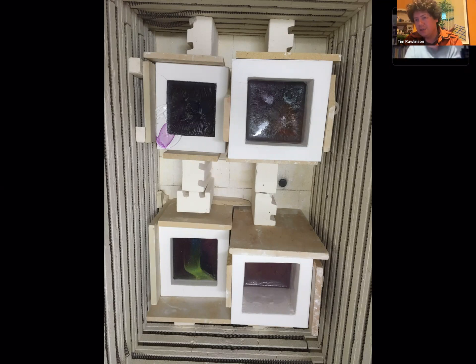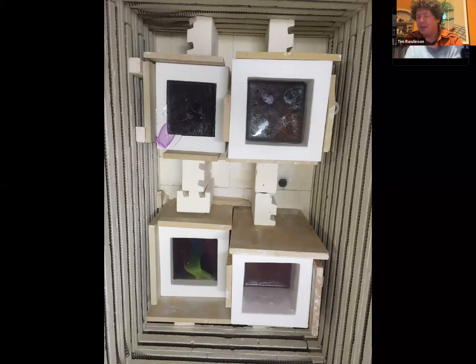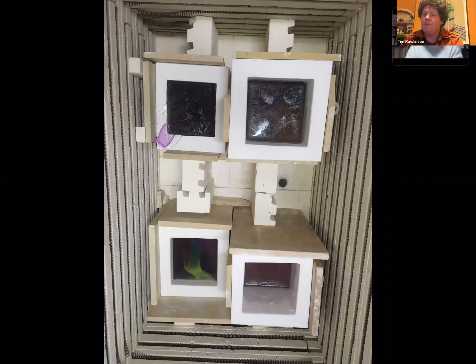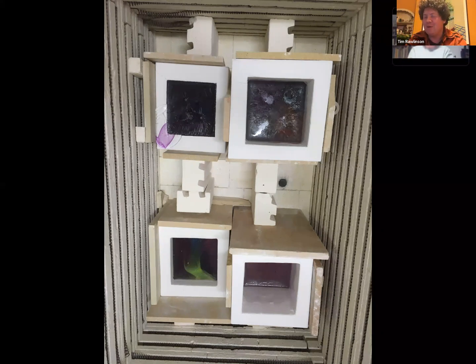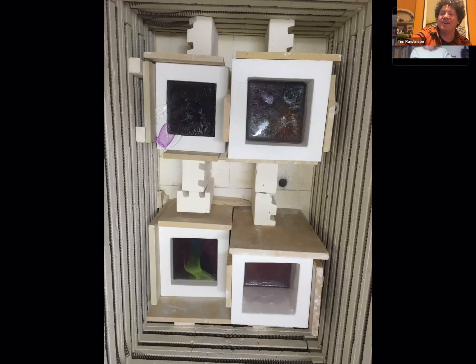It's different with Bullseye and it's different with Gaffer cast glass. But with blown glass, it drops down to 500 degrees, and then from 500 down to room temperature for a thick piece will take about a month. It's not worth rushing. When I spoke to the guy at Glasmer in Sweden about what I was doing with annealing temperatures, he was like, "This glass is for blowing tableware." He was a little bit perplexed about what I was trying to do with it, but very helpful.